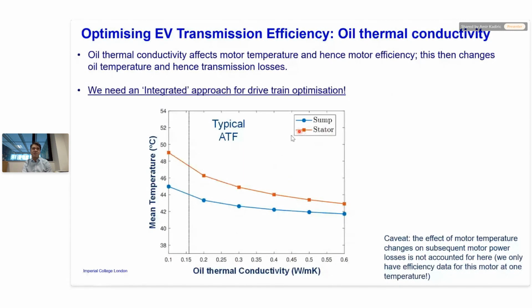So the stator temperature is shown in orange for different thermal conductivities, same viscosity. This is actually oil A, I showed you before. And the sump temperature here in blue. You can see as I increase the thermal conductivity, there's quite a big drop in the motor stator temperature, I'm predicting at about 5 degrees drop. Now that sounds little, but it's a significant effect, I'm told, I haven't seen the figures, on the motor efficiency. We are working on getting those figures. So the higher the conductivity, it appears, the better.